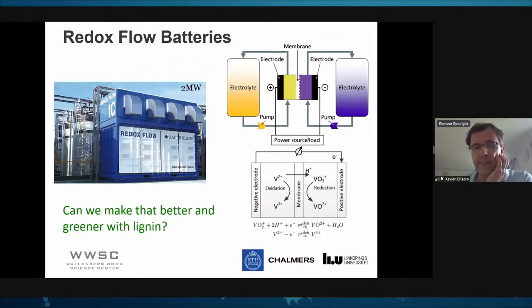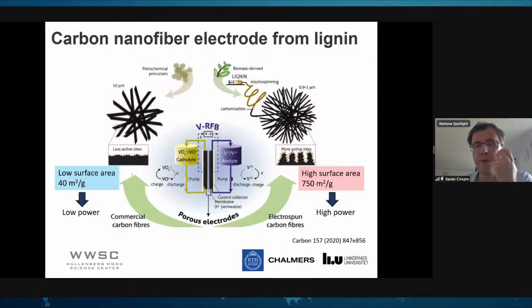So one of the things that is important is to have a very, very porous electrode, to have a lot of surface exchange between the electrodes and the liquid. So the more nanoporosity you can bring to your electrode, the better it is. And this has been one of the strategies. Instead of using common carbon fibers that are 10 microns in diameter, it has been to use lignin and do electrospinning of lignin to get nanofibers, and then carbonization to get basically a carbon conductor at the nano dimension. So lignin has been used to form nanofibers by electrospinning followed by carbonization, reaching a much higher surface area, and this means basically higher power for your battery.